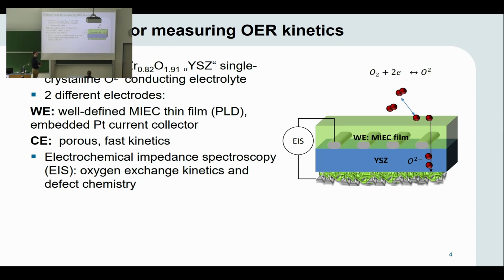And since we want to use this as an electrode, we usually need to supplement an additional current collector, which is a photolithography defined platinum grid. And this gives us the electronic conductivity of the film. Furthermore, we need a counter electrode because we want to use this in an electrochemical cell. Therefore, we have a recipe for a porous GDC-based electrode, which has very fast kinetics and is stable in oxidizing and reducing atmosphere. And with such a cell, we can then measure the oxygen exchange activity and get information on the defect chemistry by electrochemical impedance spectroscopy.